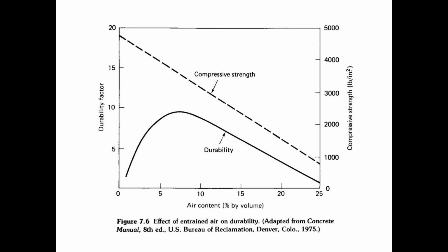Now notice the compressive strength. As air content goes up, we get a linear decrease in the compressive strength of the concrete. So the more air entrainment we use, the more adversely, negatively affected the strength of the concrete is going to be. So for these two reasons, what we generally want to do is use a water cement ratio that is right in the middle of where we want it to be. We don't want to exceed the amount of water that's needed. We want to keep a low water cement ratio.